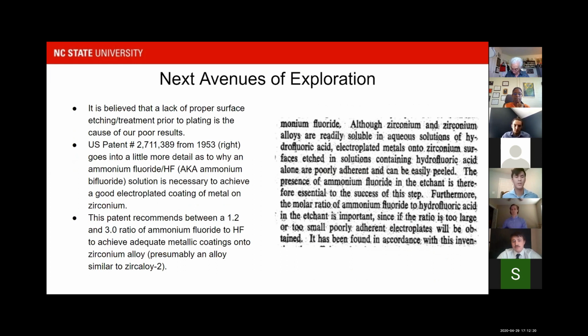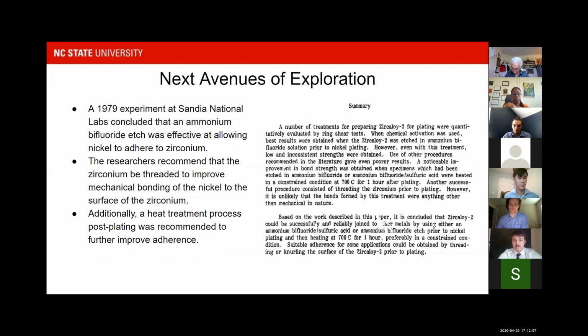Yes, as Nick described, we realized that our surface treatment was lacking. The perchloric acid probably wasn't effective enough in treating the inside of the tubing. We found literature that talked about ammonium fluoride, HF, so ammonium bifluoride, to etch the inside of the tube so that the nickel can properly adhere onto the inside of the tube. It recommended between a 1.2 and 3 ratio for adequate metal coatings. Next.